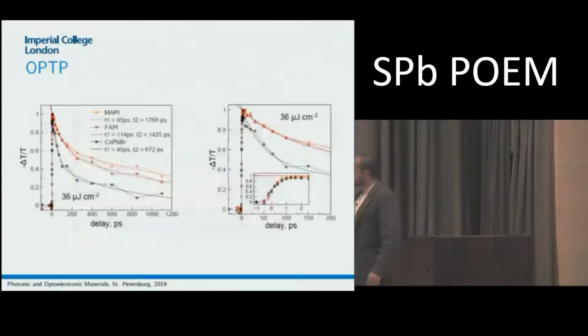the signal. I'm not looking into the time domain curves for terahertz radiation, but these measurements are done in a full 2D scan, where we scan both the terahertz field in time domain and we change the delay time for the pump beam. This is just the amplitude at the maximum. It's not the spectral amplitude yet, but the amplitude of the maximum of the terahertz pulse.